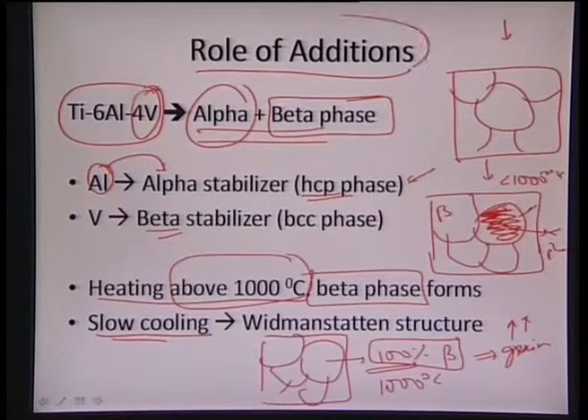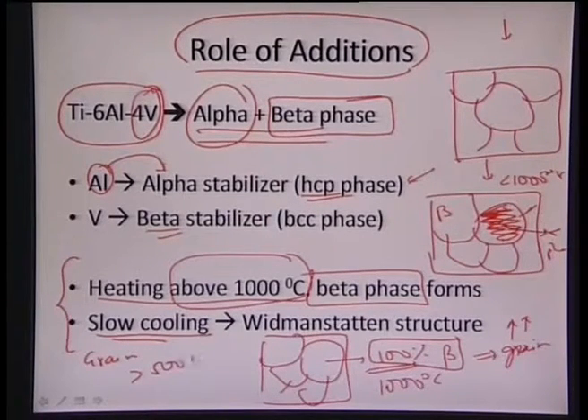So we may not achieve that sort of strengthening or toughening what we are really expecting to see in this particular material. So that is the way we need to modify somehow in terms of the heat treatment, so that we can achieve a structure which is much more compatible in terms of its mechanical properties. So though it has certain advantages in terms of its additions, this slow cooling is inducing some deleterious effects in this particular material, and the grain sizes can basically be more than even 500 microns, and at this particular grain size, the mechanical properties will be very inferior because of the Hall-Petch relationship, because our grain sizes are of the order of more than 500 microns.